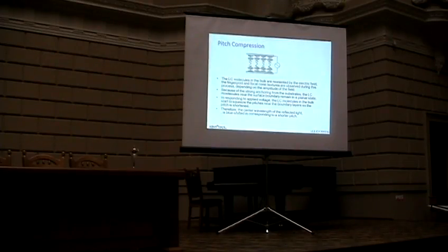Okay, so we thought about that instead of an electric field, we'll see if we can put some material into polymers. Before we apply the field to unwind this helix, we use heterogeneous materials to confine them and hold them up. There are several approaches to this. You can put all kinds of stuff in there, but in this case it is polymer. If you lightly crosslink them, with an appropriate amount, you are able to confine those pitch extensions before they fully extend, and then you can shift the color of the Bragg reflection.